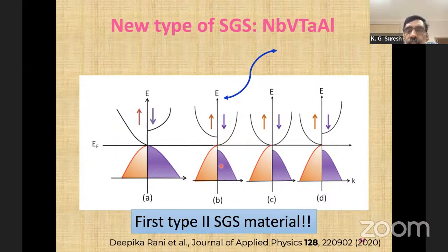The way the gap occurs can happen in various forms, and this is what is known as type 2. In this particular case, experimentally, it's very difficult to say whether it is this or this, but with a detailed DFT with all the approximations minimized, one can actually show that in this particular system, this is the kind of spin gapless nature that we have. So it's not the normal one like this. So it's not type 1, it's type 2 in this particular case.